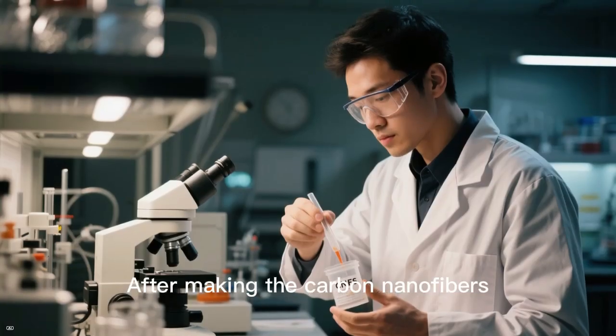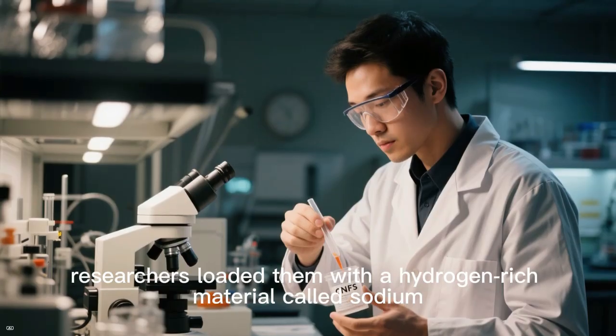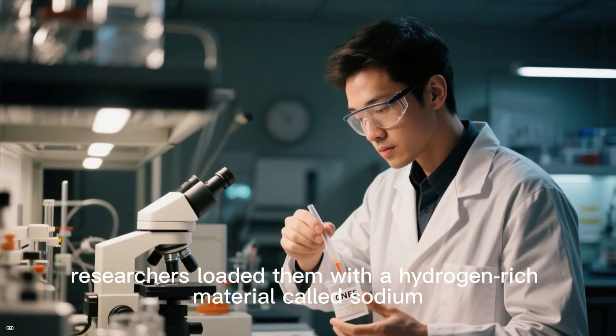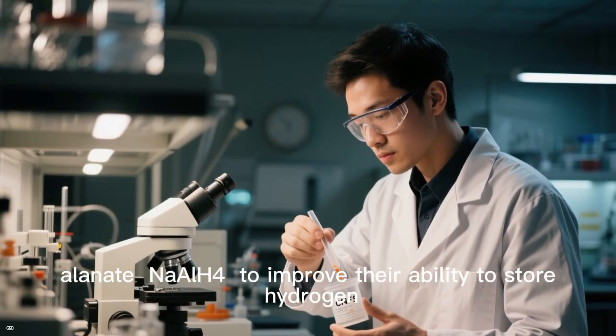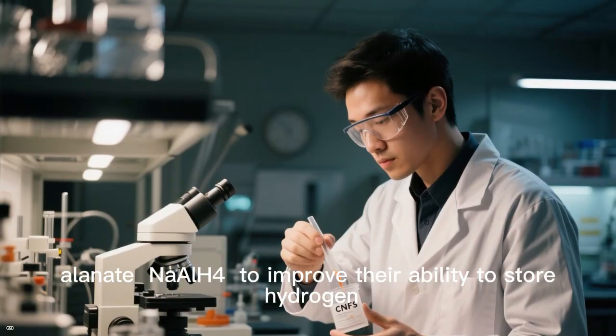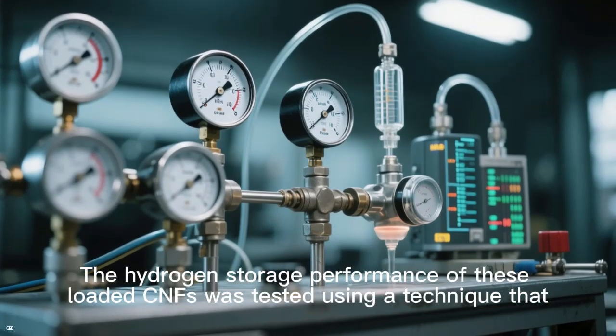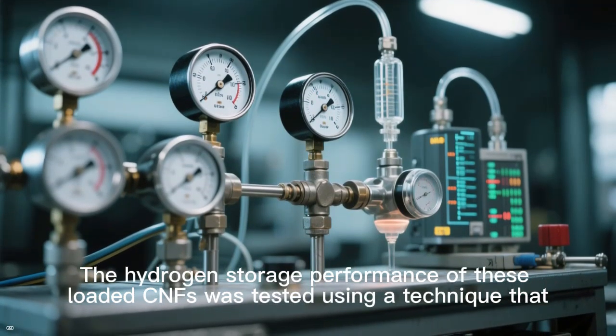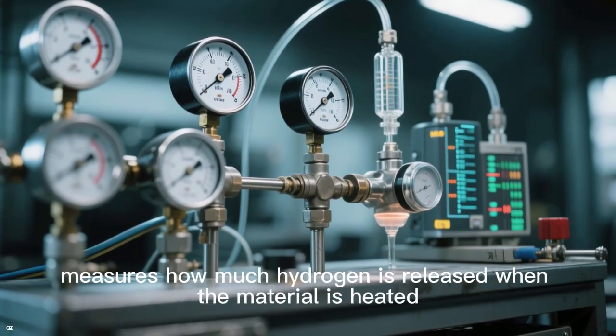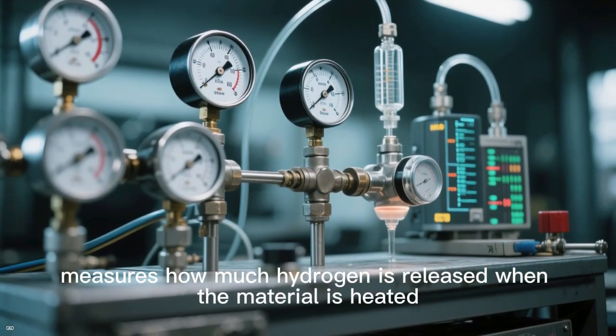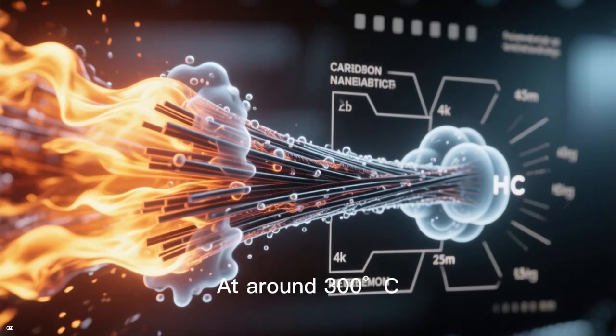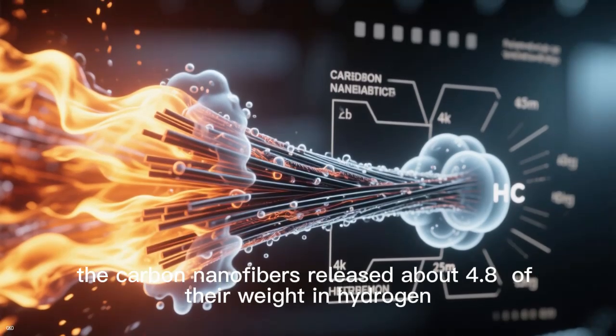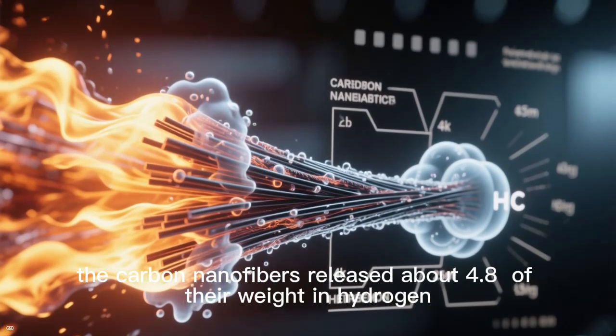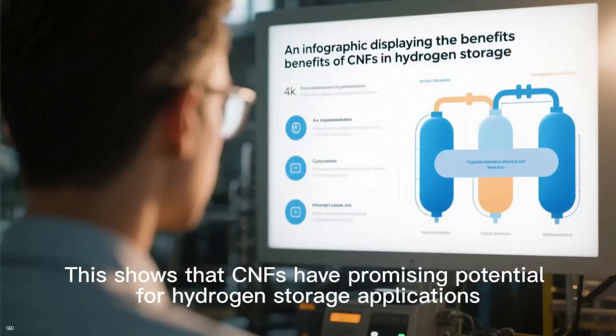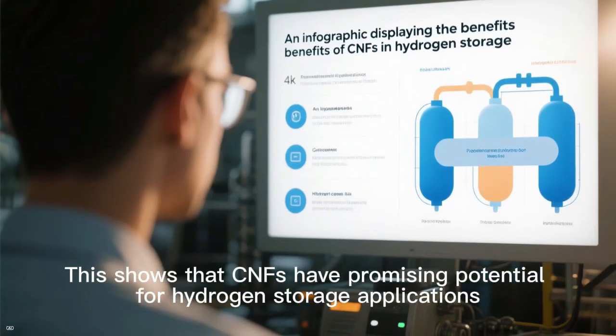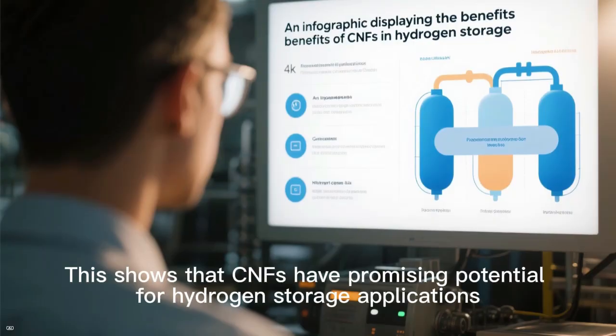After making the carbon nanofibers, researchers loaded them with a hydrogen-rich material called sodium alanate, NaAlH4, to improve their ability to store hydrogen. The hydrogen storage performance of these loaded CNFs was tested using a technique that measures how much hydrogen is released when the material is heated. At around 300 degrees Celsius, the carbon nanofibers released about 4.8% of their weight in hydrogen. This shows that CNFs have promising potential for hydrogen storage applications.